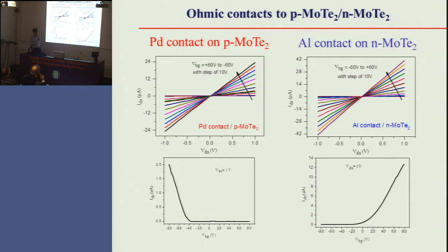So next thing is P-type MoTe2 characteristics by applying a backgate. Okay, so this is the current conductance. With a negative backgate, it shows conductance, which means this is P-type. With a positive backgate, you have a flowing current, which means an N-type semiconductor. So this MoTe2, after being shined by the deep UV with the nitrogen gas, becomes like this. So with a single MoTe2, I can make P-type as well as N-type.